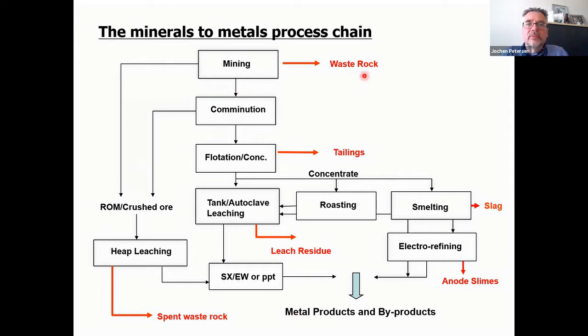So in mining, we have waste rock. You have to dig a shaft, or clear away overburden material that contains no values, and put it onto a waste disposal site. Flotation or concentration processes is where the key separation takes place. Often minerals are concentrated from ores by a factor of 50 or 100, and so a large portion of the material will go into a residue, a tailings impoundment. And we must bear in mind this comes out of a comminution process, so this is very fine material. Leaching obviously will generate a leach residue, whether that is preceded by smelting and roasting or not. Those are much smaller volumes, but quite often they contain quite a lot of hazardous residues.